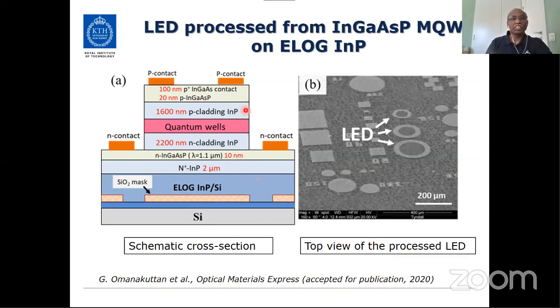So this is the structure which we have grown. We grew only ELOG indium phosphide on silicon, and here these structures were grown by MBE, and these were processed as LED. This is a top view. This is a ring contact, so the light will come out from the center. Okay, so this is a ring contact here.